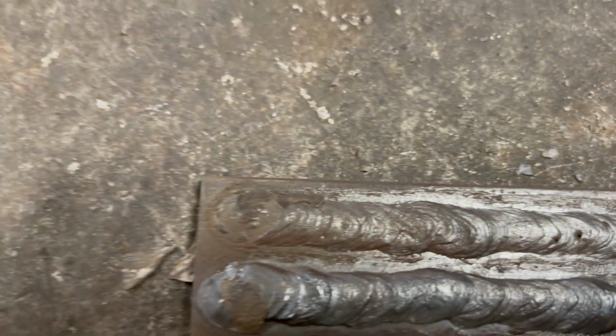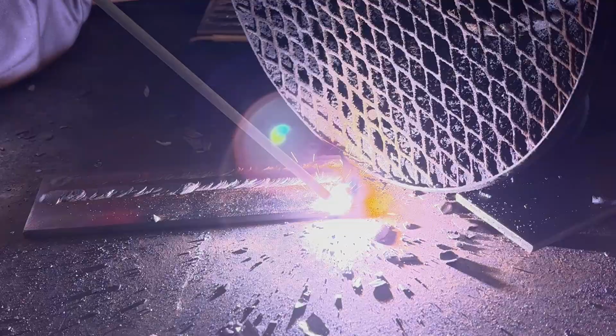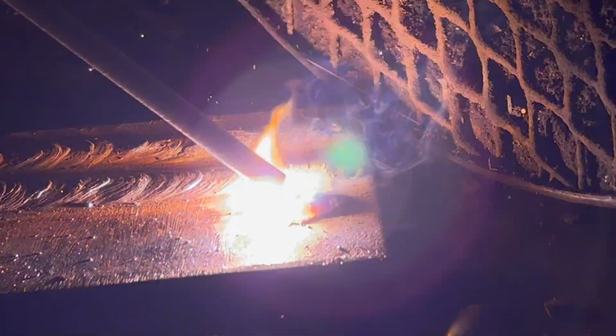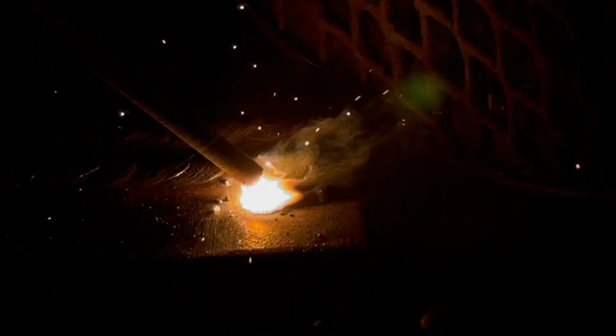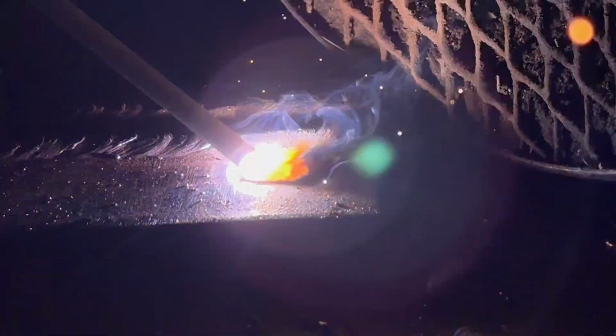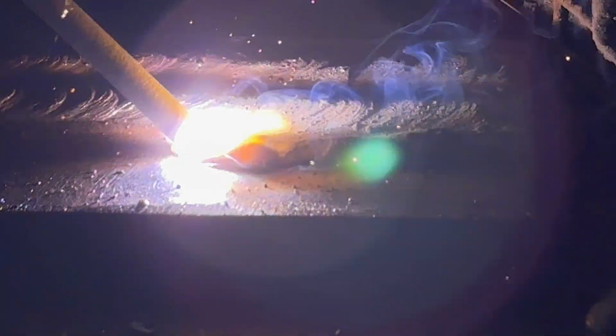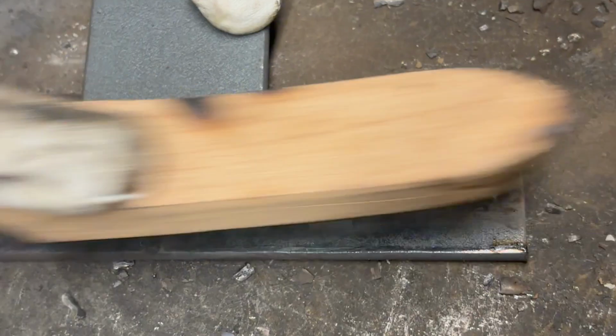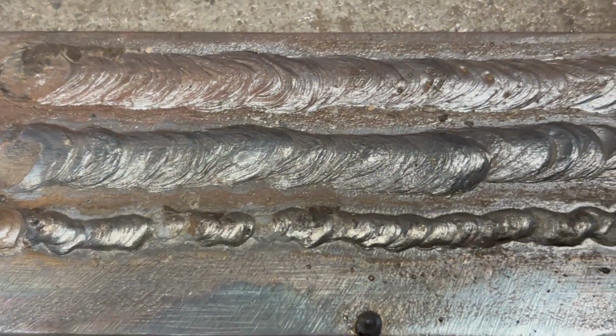On this next run, we're now going to drop our amperage down. So instead of welding at the correct amperage, which is 125 amps for these rods, we're dropping down to 60 amps to show you the effects of welding with the incorrect amperage. As you can see, it's difficult to maintain a stable arc at this low amperage. The rod struggles to stay lit, making it harder to control the weld pool and produce a consistent bead. This will always lead to poor fusion, uneven ripples and a weak weld overall. It's often the mistake that beginners make when trying to get the correct settings, which, as you can see, makes a massive difference to the weld quality if you get it wrong.